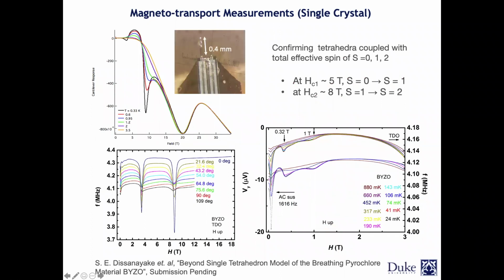So one of the things that we used, for example, was the TDO again, but we go to 24 millikelvin or very low temperatures, because these excitations are going to be very weak. Are we going to see anything? And in fact, we saw. For both the AC susceptibility and the TDO data, we started to see these wiggles that are happening in this.